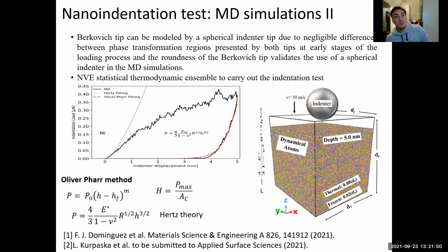The next step is to define the sample here. And this is the indenter, the spherical indenter. The indenter will go in this direction to touch the sample, then it will dig deeper and deeper. So this is a spherical imaginary tip that needs to be defined by an initial load and also an indentation rate. All of this needs to be in good agreement with the experiment.